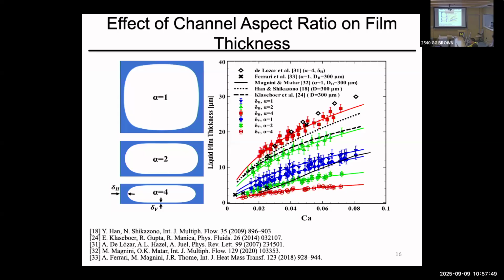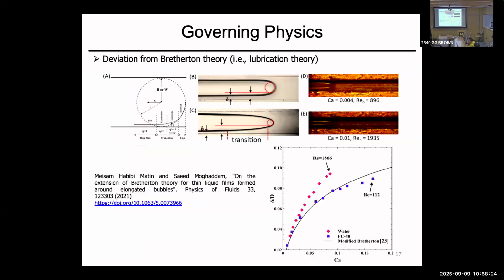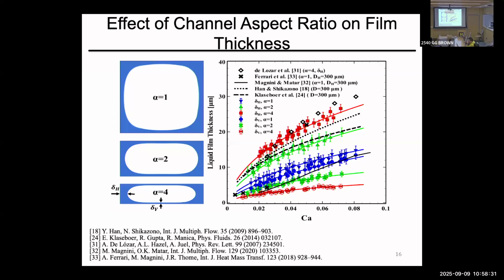And so basically we started looking at the different governing equations, and what we realized is that up to a certain capillary number, you can, to some degree, based on what fluid mechanicians did, Bretherton particularly in 1960, it's a balance between viscous forces and surface tension. So up to a certain capillary number, you have some predictability, particularly in a square channel. Obviously it was developed for round, but if you start going to high aspect ratio structures, you start deviating from the existing models. Just to give you very quickly, Bretherton's trend shows a 2/3 scaling with the capillary number for a bubble.